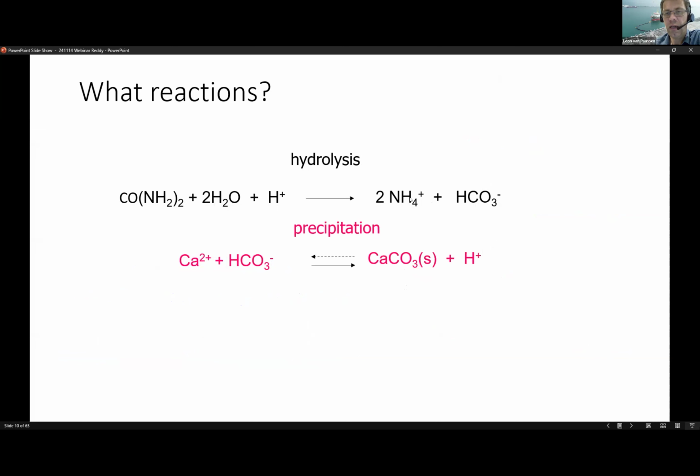So altogether, the reaction should be pH neutral, and the pH should not increase as a result of that. But again, this is not so simple because calcium carbonate is a polymorph, which means that there are multiple different crystals. You might form amorphous calcium carbonate, you might form vaterite, or you might form calcite.